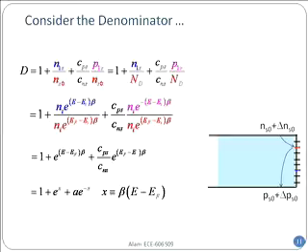So let's say we find the Fermi level. Fermi level is known. E is whatever trap I'm talking about. So it is 1 plus e to the x plus some constant, which is the ratio of the capture cross sections, and e to the power minus x. Do you see the minus sign in this one? E minus EF and EF minus E. So there's a minus sign. Well, I'm in good shape now. I'll be able to integrate this.